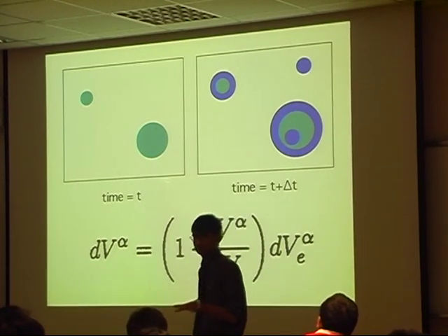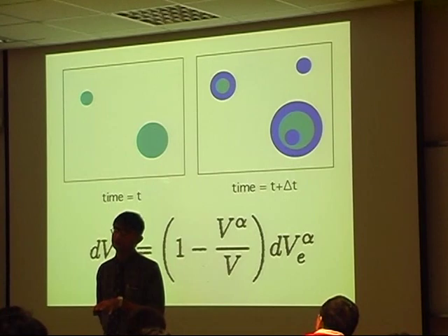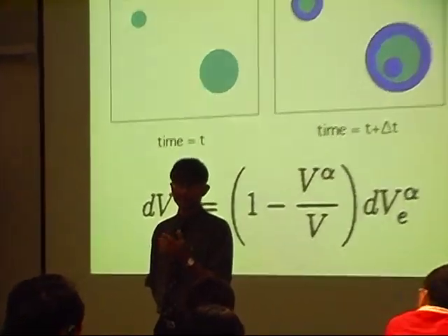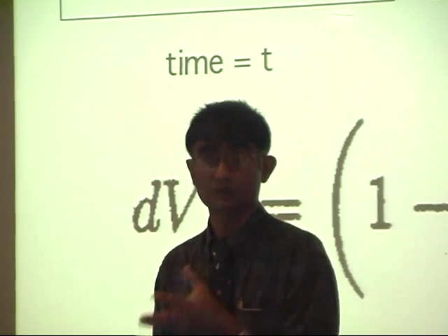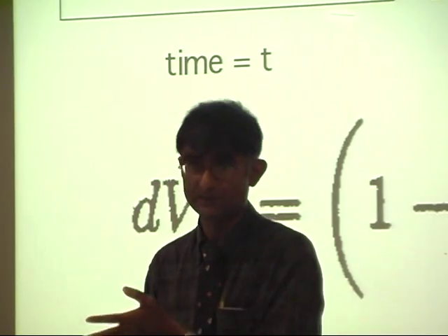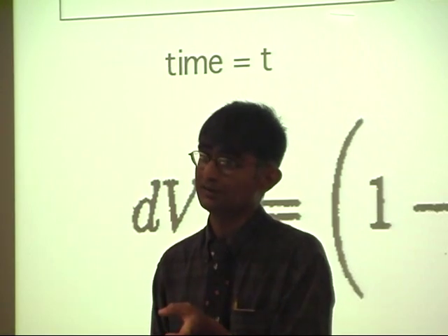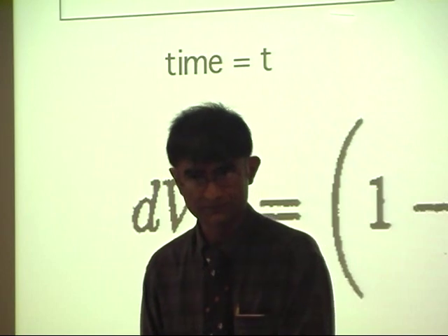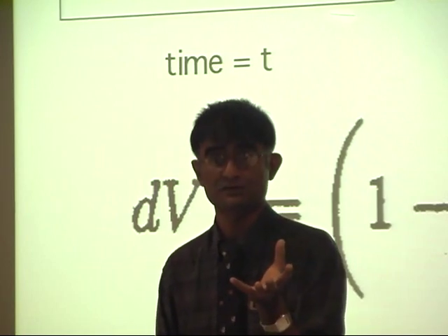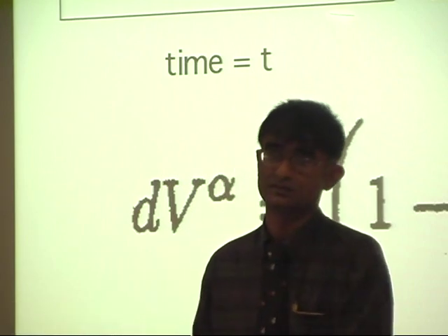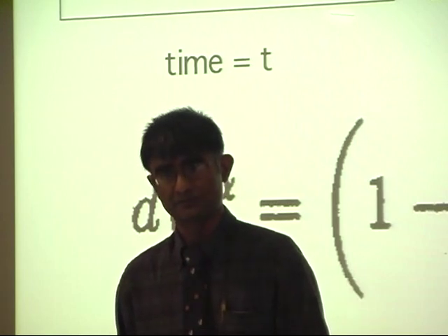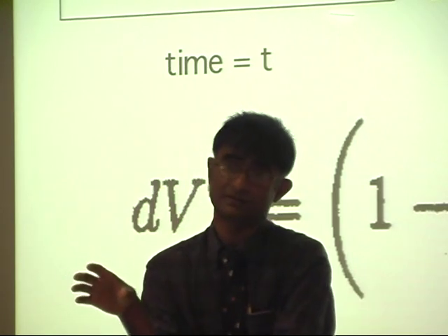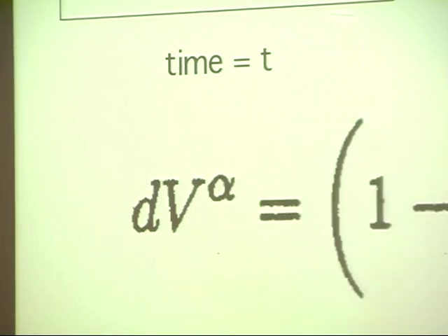It is true that thermodynamics deals with equilibrium. We can also deal with constrained equilibrium. For example, if manganese is not diffusing but carbon is diffusing, then you can still do a phase diagram calculation, a modified phase diagram for what's known as para-equilibrium. You can also calculate the free energy of martensite, which is not an equilibrium phase, and compare it with the free energy of austenite, and therefore work out a martensite start temperature. The only thing that would be completely missing is time dependence. But then you can put thermodynamics into kinetics. So for example, if you are working out the growth rate of a phase,